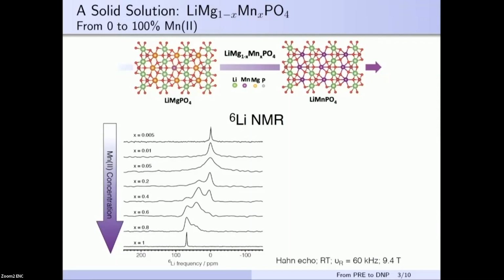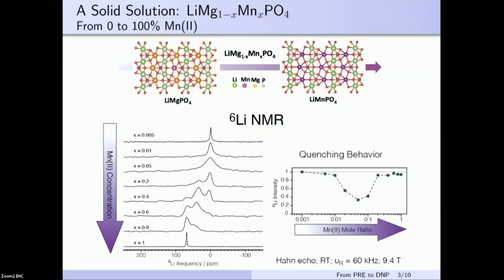So we quantified the signal intensities for all these samples, taking into account the number of scans, moles of lithium-6 and so on. And we obtained this interesting figure of the signal intensity versus the content of manganese. At low concentrations, the signal intensity was dropping, as we were expecting, because we have signal quenching. But there is a point where this trend reverts, and further increasing the manganese content allowed us to see more lithium nuclei again in the sample. And at the very high concentration, we were able to virtually see all lithium again.